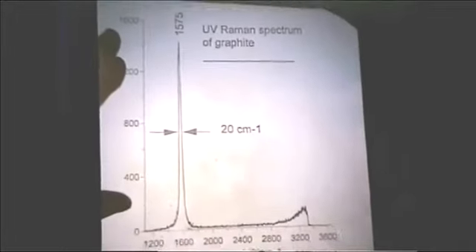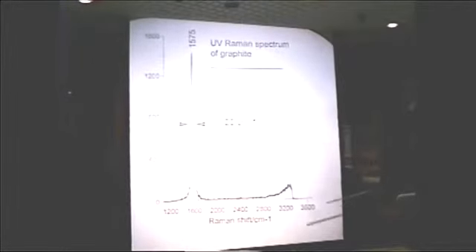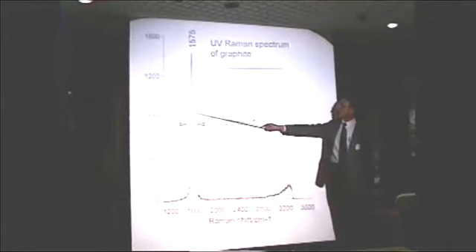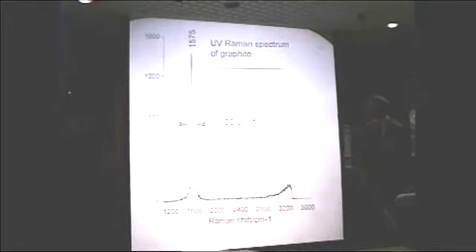Now, just to orient you in terms of where we might expect coke bands to be, let's look first at graphite and see where that is. Here's the Raman spectrum that we get from graphite, and you get a very nice Raman spectrum. This peak out here is basically an overtone of the graphite vibrations. And this strong Raman scattering peak here at 1575 is very classic for highly crystalline graphite. Now you remember the other bands that we saw were up above 1600, so they're in a completely different spectral range than this. So they really are not graphite. We know that right away, basically just by making that simple comparison.